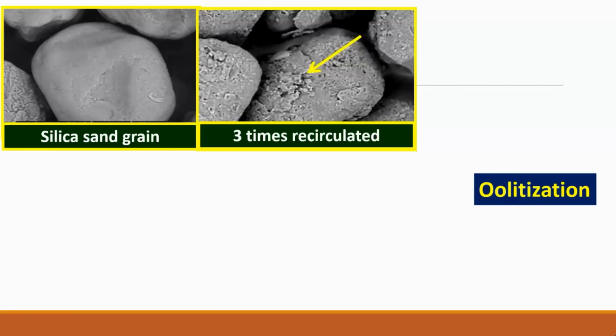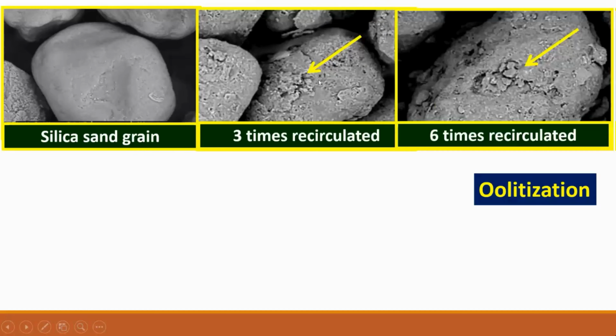When it is 3 times recirculated, someone has done this experiment, so I picked up this picture from them, you will see that some layering has formed on top of it. And then when it is circulated 6 times, you have got more and more layers one over the other sitting on the sand grain. So it's not uniform, but it is there in some places, here, and here. So generally, there is a weakening of the refractoriness over a period of time due to multiple circulation of these sand grains inside the system.